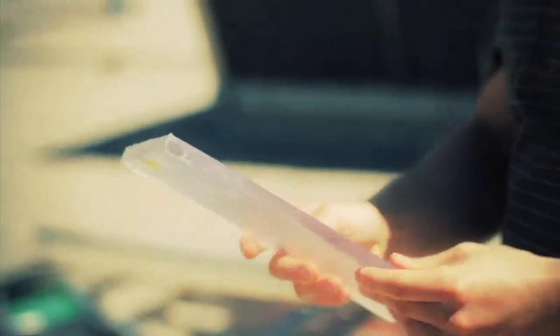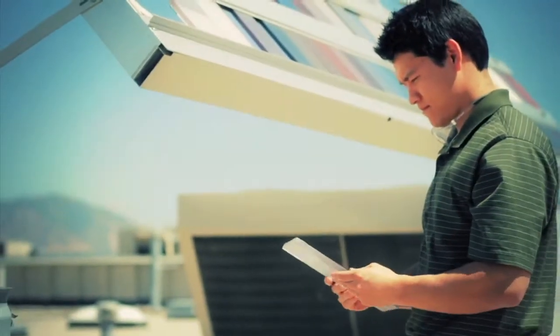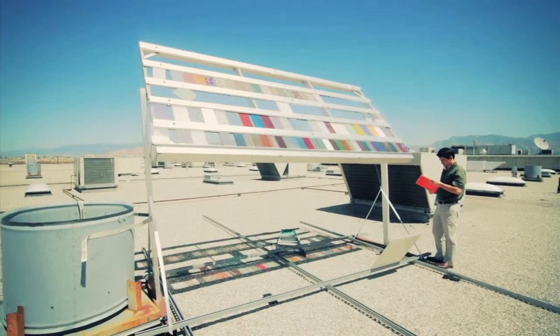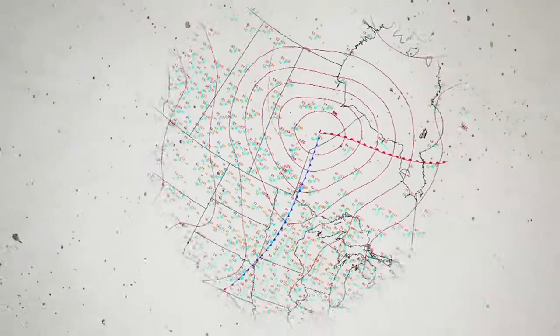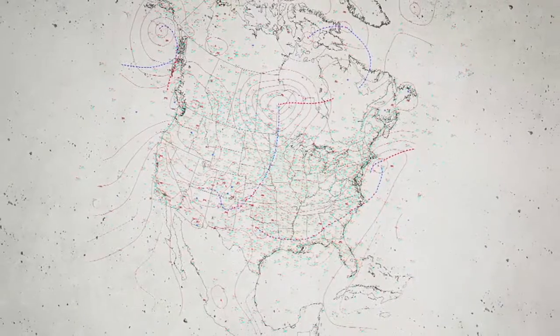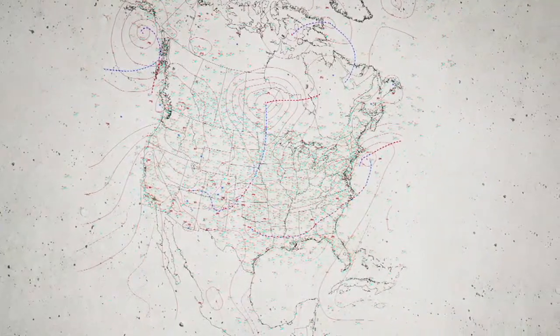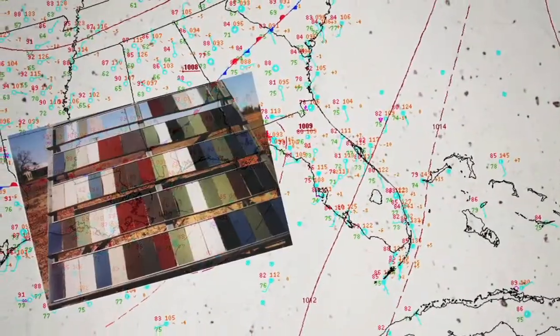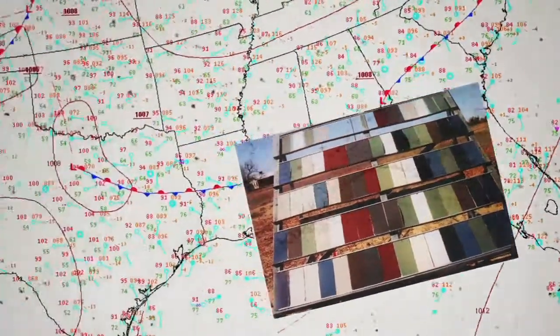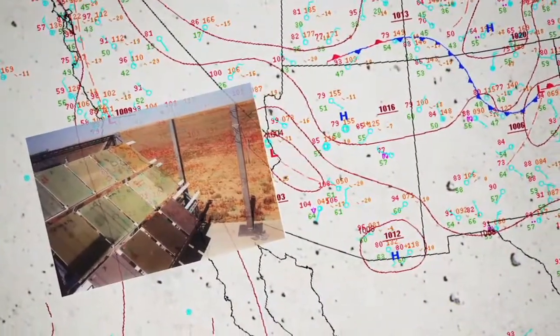And in testing methods in the United States specifically, it's really good to have 2 different test zones. Globally, the 2 most extreme environments would be the tropics or the deserts. In North America, we have both. It's very common to look at test results that come from South Florida or from the Arizona desert. These conditions are simulating 45 degrees, south-facing, fully exposed conditions.